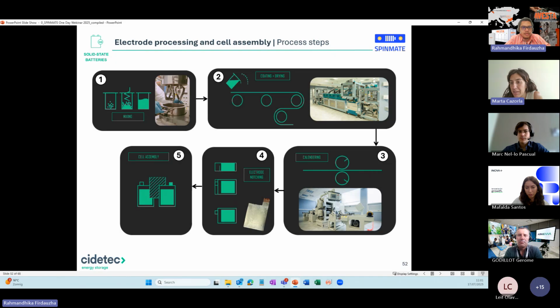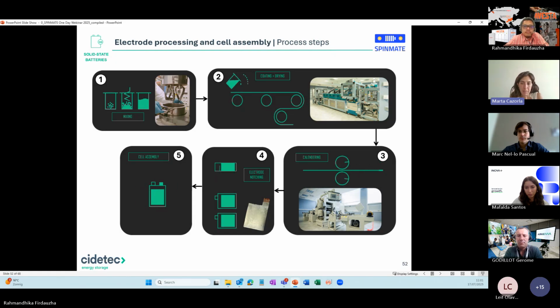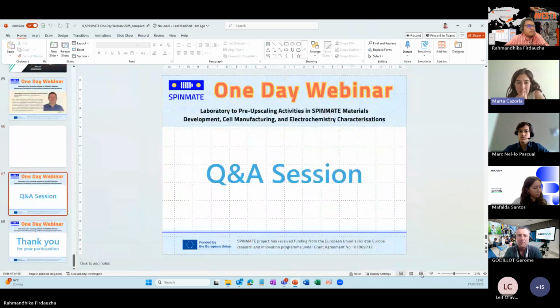Yes, I can answer for both. To make the pouch, we don't apply a certain pressure. The stack is assembled, and then we seal the cell under vacuum, and then we apply pressure. So during the assembly, there's no pressure applied. It is when we mount the cell in the jig at the ending step. The cell on its own will not work, so we control the pressure with the jig in this case.